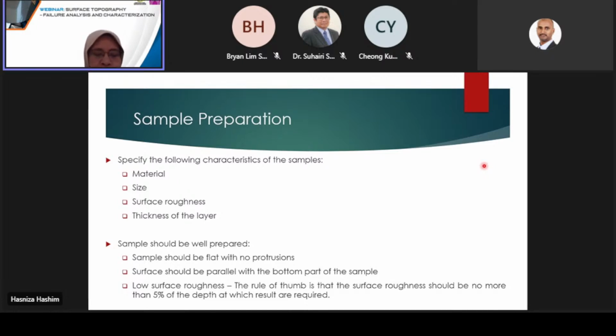Okay, before we do the indentation, we need to specify the following characteristics of the sample. If possible, we need to know the material of the sample for testing. We need to know the size of the sample. Also, it's very important if you can know the surface roughness of the sample before we do the indentation, and also the thickness of the layer, if the intention of our testing is to measure the material properties of the top layer.